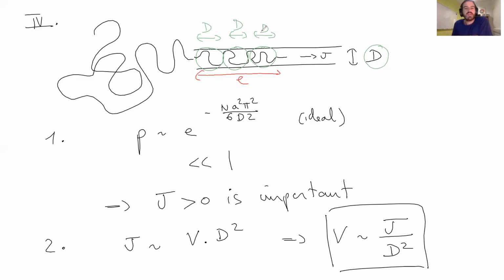So if I want to estimate for such a configuration, what is the free energy or the excess free energy with respect to the situation where I was not entering the pore? Well, I have to remember simply that each blob is independent from the other and has a free energy, which is kBT. We say kBT per blob. That's the main message. There is kBT per blob, and therefore, the free energy of confinement, let me call it conf again, is kBT times the number of blobs inside the pore.